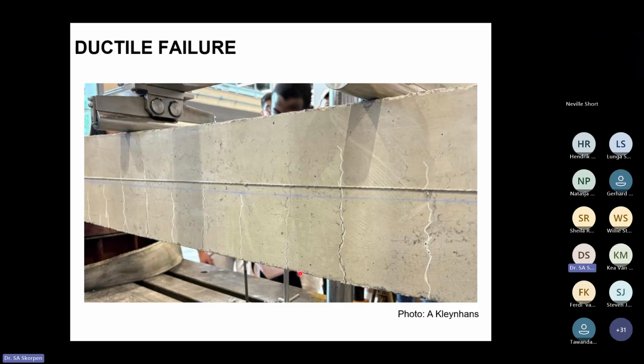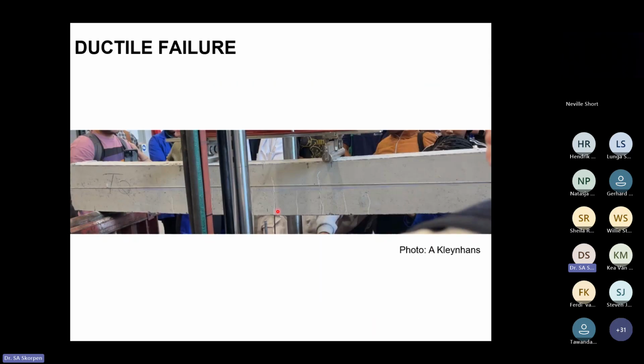There's flexure happening here. You can see these crack widths. If you only had one crack, then there's probably very little bending happening here. That would be synonymous with some kind of restraint, such as restrained shrinkage. But when there's flexure, you would see these fairly uniformly distributed cracks, so that you can follow the curvature of the beam here. And there's another view of this, just showing the bend. You can actually see the deflection here, and you can see these uniformly distributed cracks.